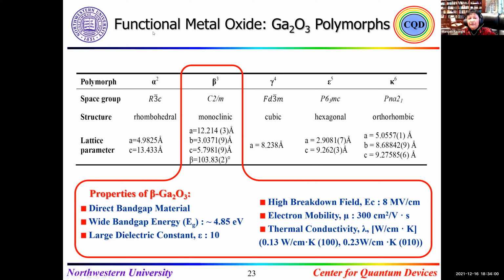Now we are coming to the functional metal oxide, gallium oxide, which is polymorphic. Like perovskites, they have different phases, and the change of phases is a huge subject of research. They showed that beta gallium oxide, with the monoclinic structure, has a direct band gap and wide band gap of 4.85 electron volts, has large dielectric constant, high breakdown voltage, and high mobility. But one problem: thermal conductivity is not good.